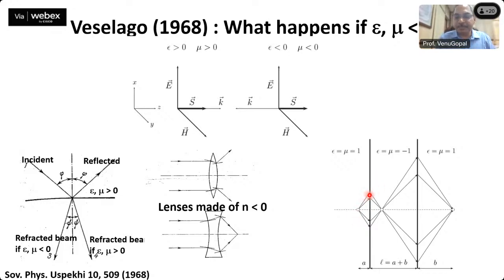And what happens is that at the interface there is a change from n positive to n negative. So by virtue of it, with e to the power ikx, you'll no longer have a diverging beam inside the negative index medium. It becomes a converging wave. Like all those components, high k vectors, which are actually evanescent in the positive index medium, will become non-evanescent, propagating waves inside this. So all the high k components in the incident beam get lost because they're evanescent if they propagate in a positive index medium.